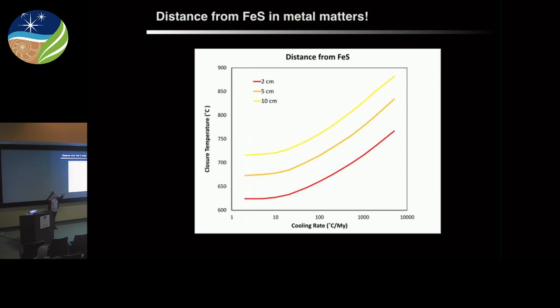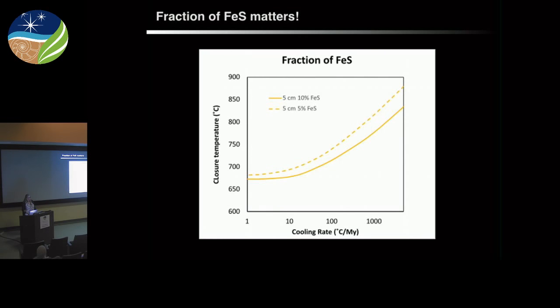And now we're talking about diffusion in the metal, not the troilite. The silver is in the metal, and it depends on how far away from a troilite grain you are. So that's what these distances are here, the distance from a sulfide nodule. You can get higher closure temperatures by measuring things farther away from a troilite nodule. And if you measure something close to a troilite nodule, that silver is still trying to get and able to get into the sulfide and diffuse away from the metal that it's in. So the closure temperature depends on how far away from a troilite nodule you are, as well as cooling rate. It also depends on the amount of troilite or FeS in your sample.